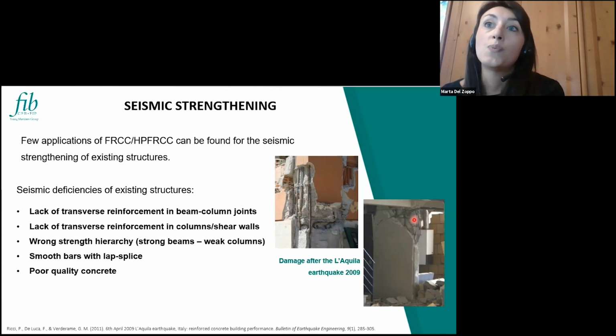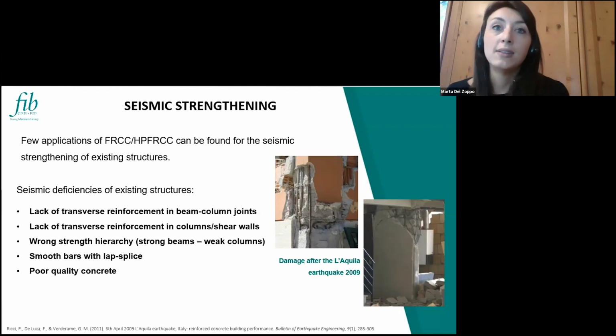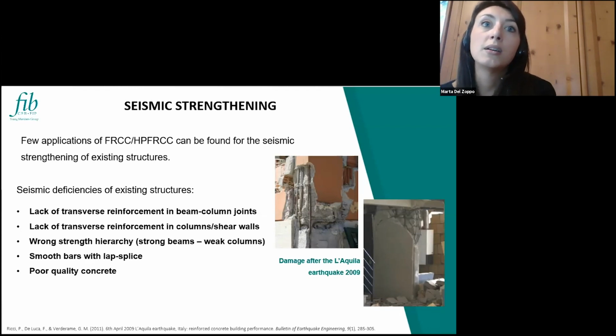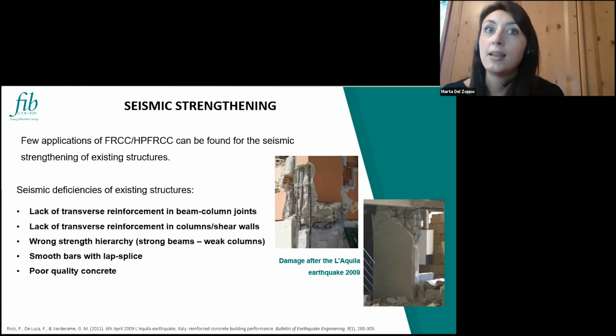The lack of stirrups or transverse reinforcement in columns and shear walls, and then other design issues related to a wrong strength hierarchy between beam and columns, but also between flexure and shear. And for buildings that were built before the 70s, usually we also have the adoption of smooth bars, with lap spliced regions, and also very poor quality concrete because the quality of materials was lacking at the time. So often we have concrete with very, very poor compressive strength.